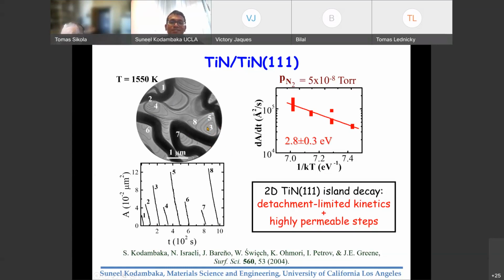This phenomenon is referred to as step permeability, which is a funny phenomenon that's not commonly observed in a lot of materials, but experimentally it has been observed in silicon and I think maybe in copper. This is the phenomenon where atoms can funnel through rather than overcome the barrier. So the decay behavior is significantly enhanced. For titanium nitride 111, at these temperatures, we extract an activation barrier of about 2.8 eV for the disappearance of these islands in this wedding cake configuration.